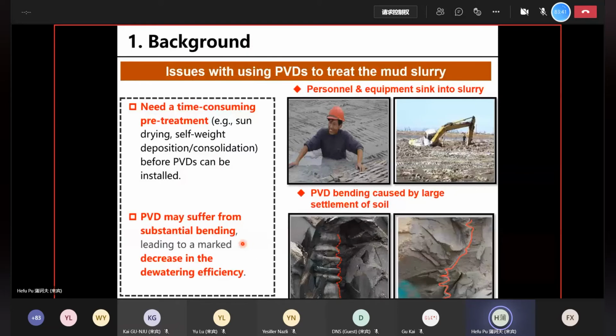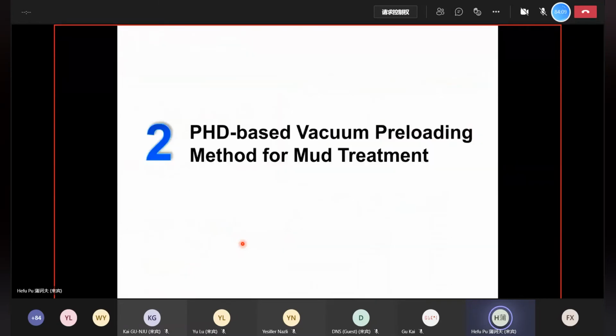Another issue is that the PVDs can be severely bent because the mud is very soft. After the treatment, after the consolidation, there will be a significant deformation, and because of that, the PVDs will be severely bent, and that can cause a decrease in the transfer of vacuum pressure, and therefore a decrease in the dewatering efficiency. So later on, people began to use the PHD-based vacuum preloading method for mud slurry treatment. Conceptually, it's easy. You just replace the vertical drains, the PVDs, with horizontal drains, the PHDs.